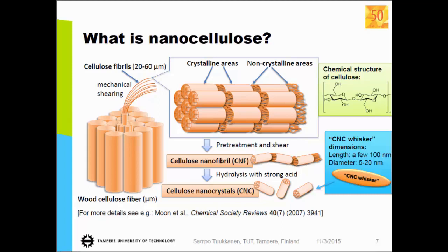So we call them cellulose nanofibrils, which are composed of amorphous parts and crystalline parts. And if you treat these nanofibrils with a strong acid, you can remove the amorphous areas, and you end up with these cellulose nanocrystals. And these are also called nano whiskers. And these are on the dimensions of a few hundred nanometers long and from 5 to 20 nanometers in diameter.